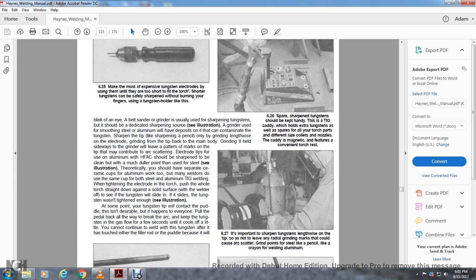At some point, your tungsten will contact the puddle. This is not desired, but it happens to everyone. Letting the pedal back all the way will break the arc, and keep the gas flowing over the tungsten for a few seconds until it cools off. Then you can continue to weld after the tungsten is cleaned or replaced.